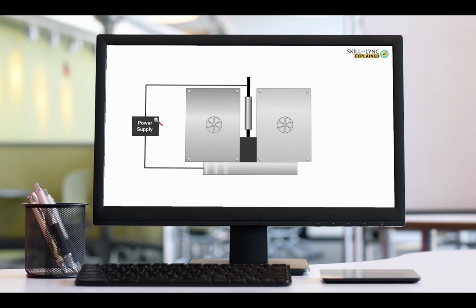The main reason why the flux is added here is that it is a very bad conductor of electricity. Because of this, when the current is passed through the molten slag, joule heating occurs. This causes the electrode wire, which is in contact with the flux, to also heat up, causing it to melt and join with the flux weld pool.